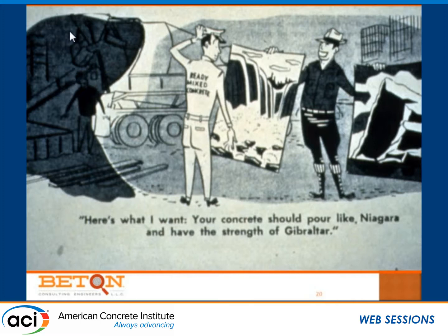So as a result, and this is an old cartoon, and at the time it was written, it was quite funny, right? Because you could have one or the other. Of course, today we can have this, this is really what we can do. We can place concretes that are a puddle on the ground that are 10,000 PSI in 5 days, that are 3,000 PSI in 8 hours, and you can stress them if that's what you're looking for.